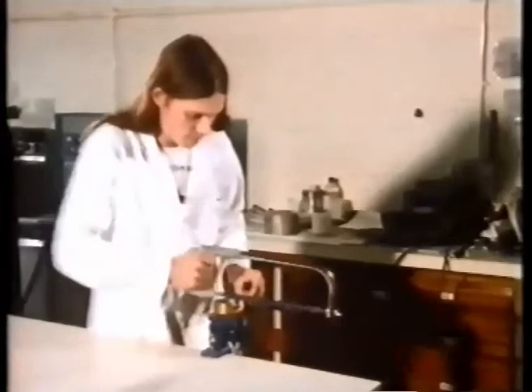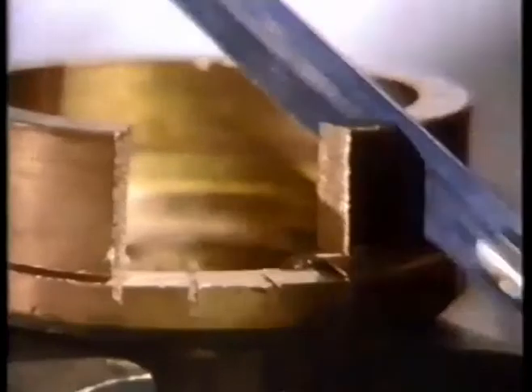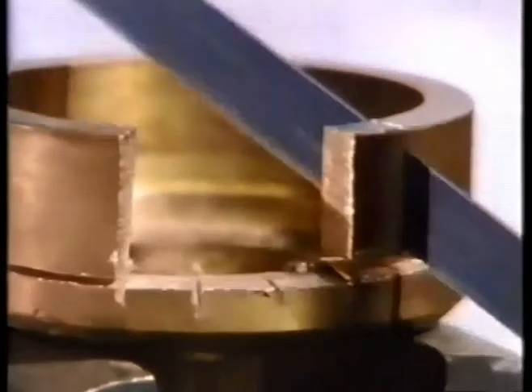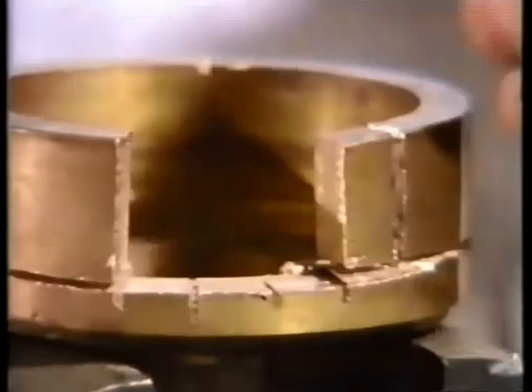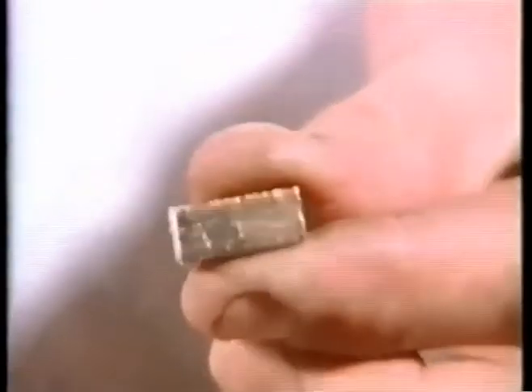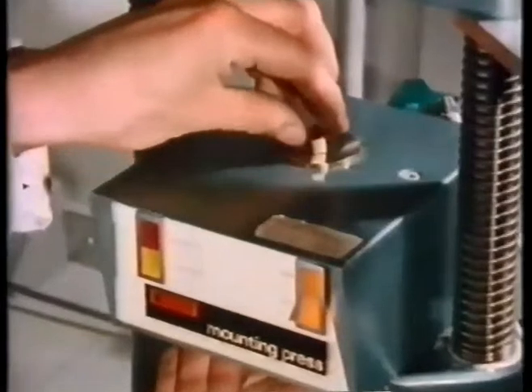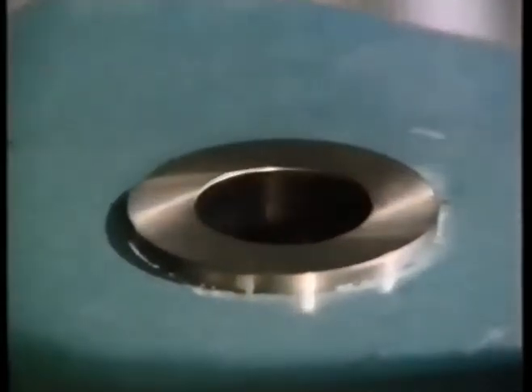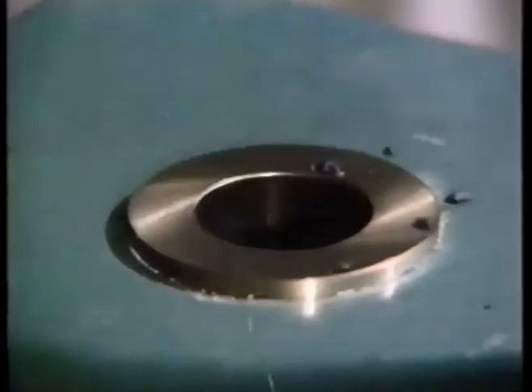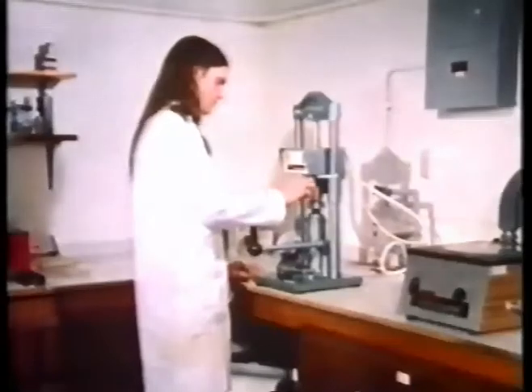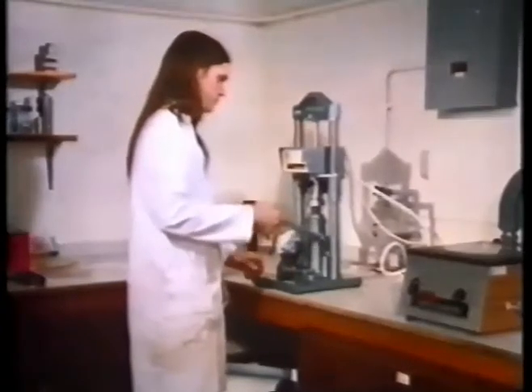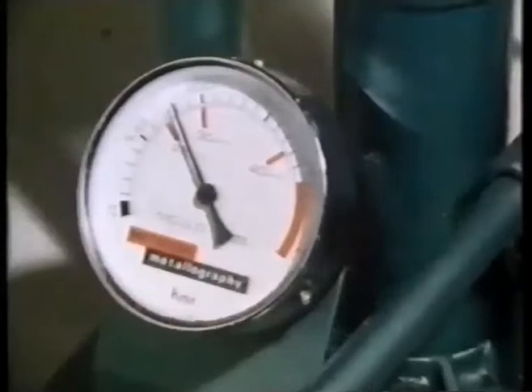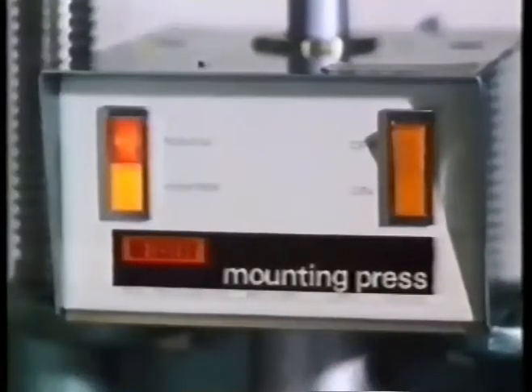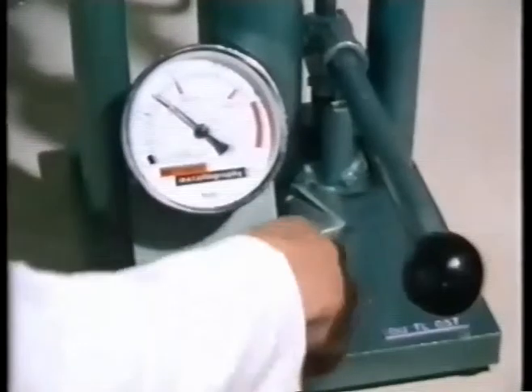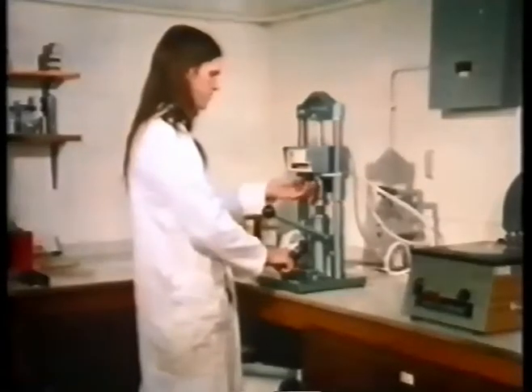Samples are taken by hacksawing out suitable samples from the bearing in question. Here's a smaller bearing, but the principles are exactly the same. And here's a transverse section. In order to preserve the edges of the sample, it's necessary to mount it in a thermosetting plastic. This is cured by applying a moderate pressure and temperature to the thermosetting compound. Once set, the pressure can be released and the temperature lowered.